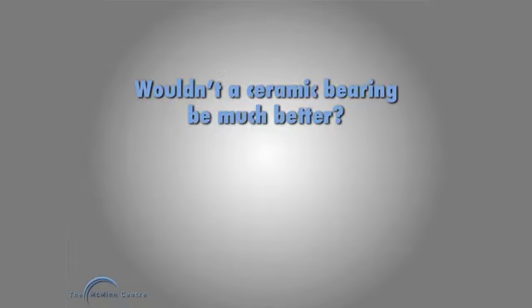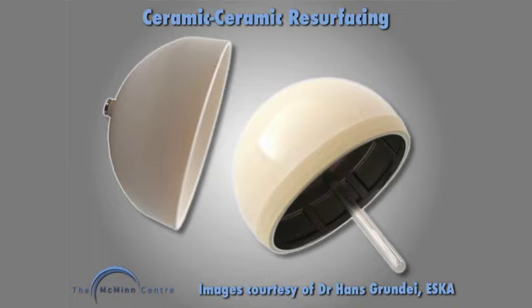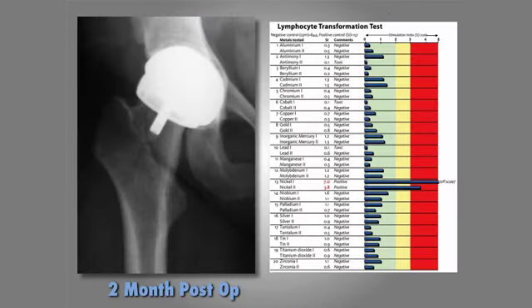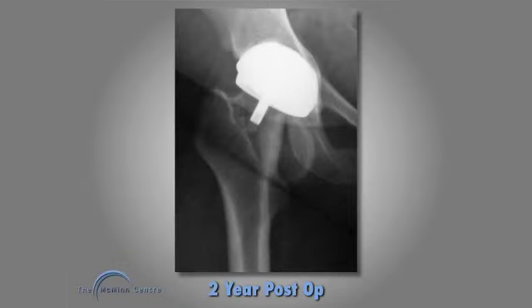Wouldn't a ceramic bearing be much better, you ask? Well, you might think so. I've carried out 5 ceramic resurfacings in patients who, like this one on the right, have hypersensitivity to nickel. Now, cobalt chrome has nickel contamination within it, and metal on metal is not good for patients with sensitivity to nickel. And I've done here a ceramic resurfacing, and everything was great to start with, but by 2 years, unfortunately, it has failed. You can see the outline of the fractured and dislocated ceramic liner, which has displaced down to the medial neck position.